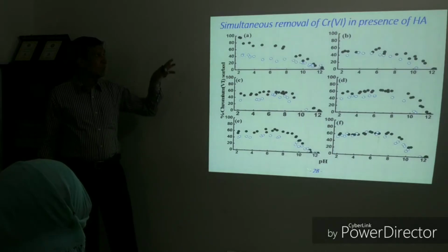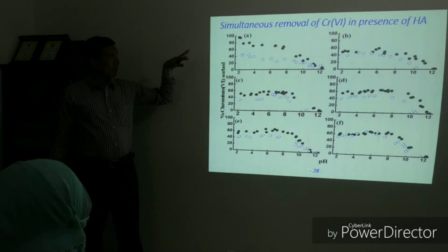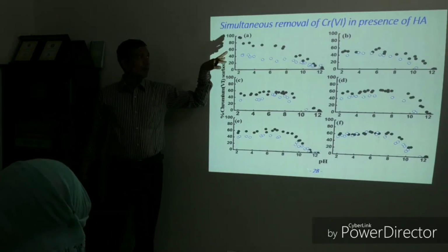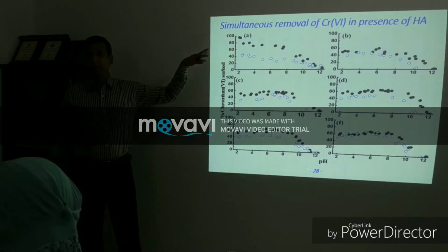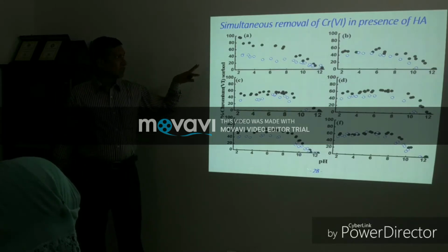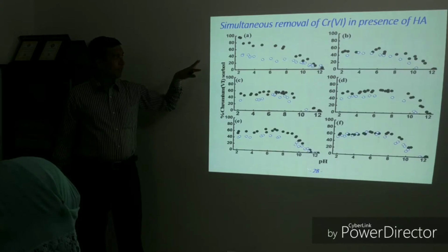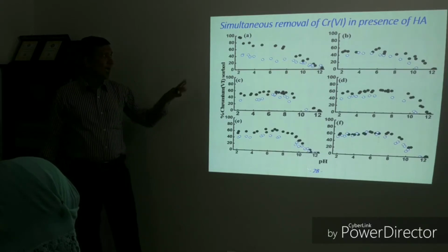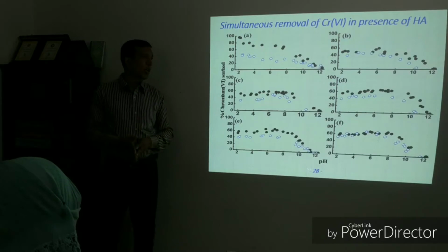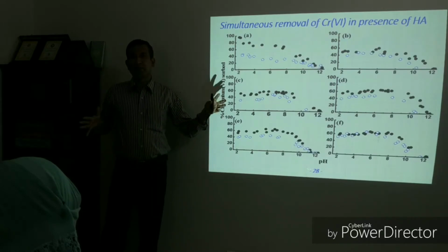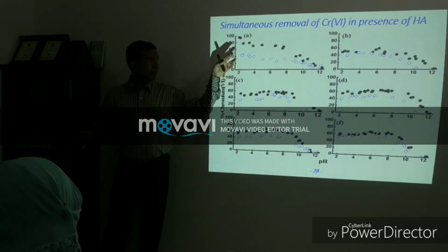Then we have studied simultaneous removal of chromium in the presence of humic acid. Here chromium, hexavalent chromium, is an anion and humic acid is also an anion. So here we also see that the presence of humic acid also decreases the amount of chromium adsorbed. This could be due to the electrostatic repulsion between negatively charged chromium and anionic humic acid.